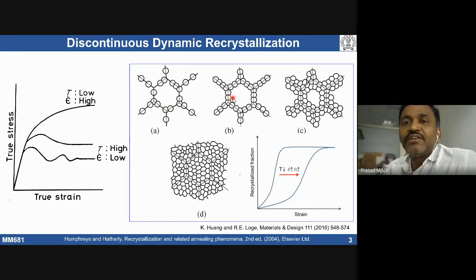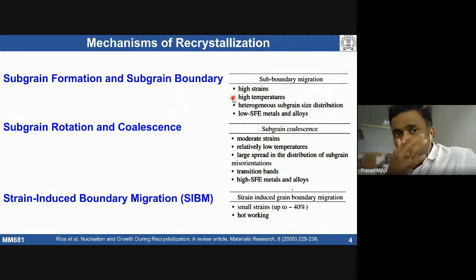So this is a characteristic way of saying that the material is undergoing discontinuous dynamic recrystallization. Then we had a discussion about the different types of mechanisms people use for saying how recrystallization is taking place in a material. It can be static or dynamic, and when you say dynamic, it can be CDRX or DDRX. The well-known mechanisms we discussed are subgrain formation followed by subgrain boundary migration, subgrain rotation and coalescence, and strain induced boundary migration. Most of the time when there is DDRX, SIBM is a common mechanism which explains formation of recrystallization in a material during deformation itself.